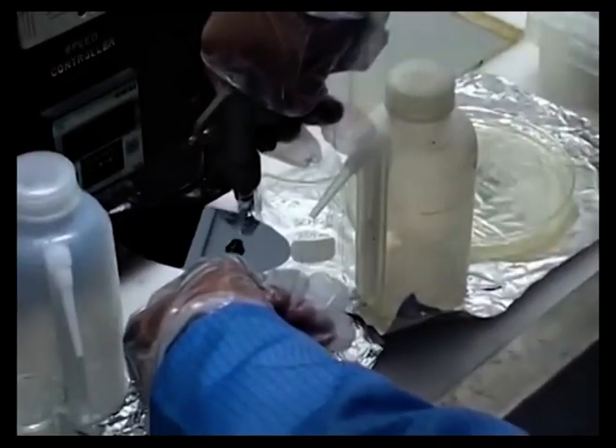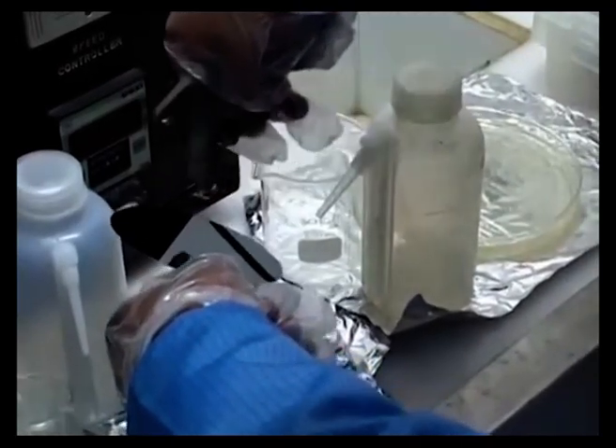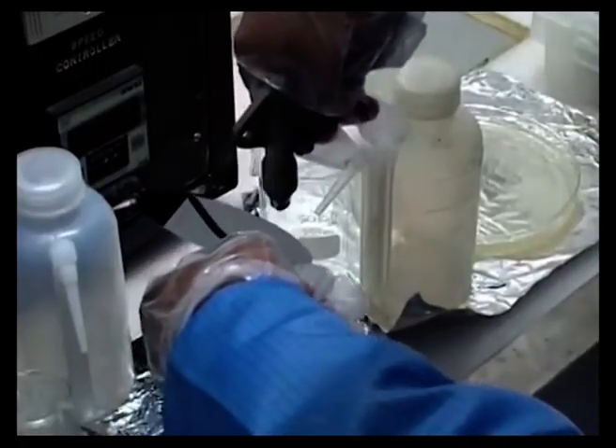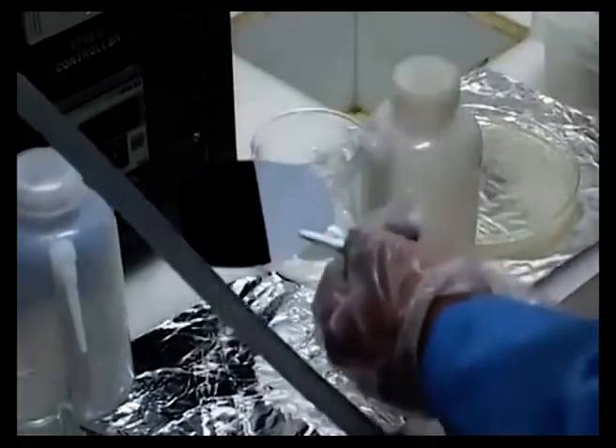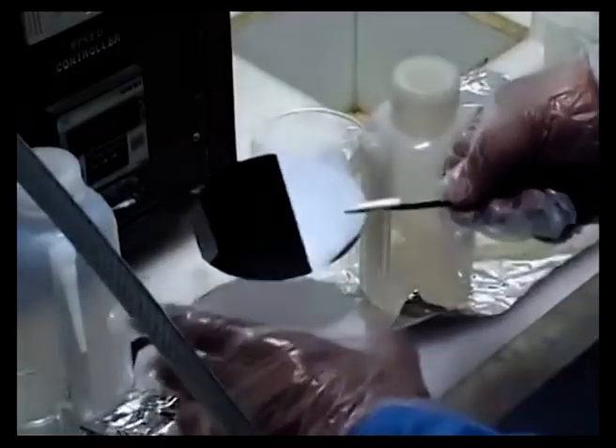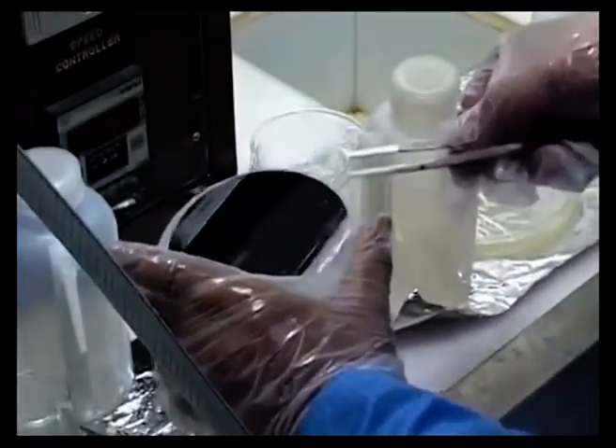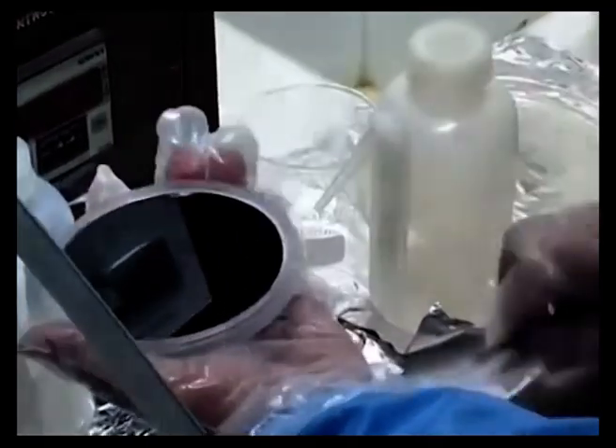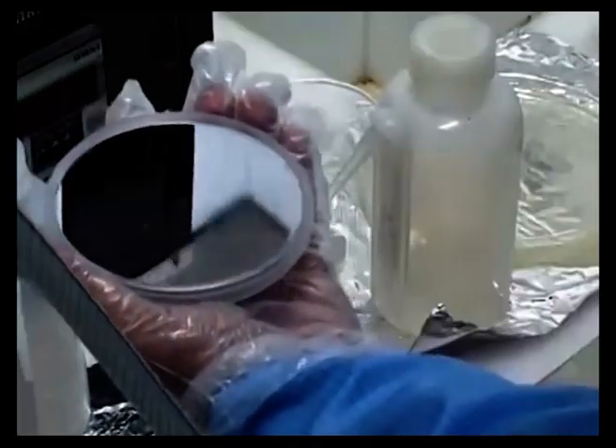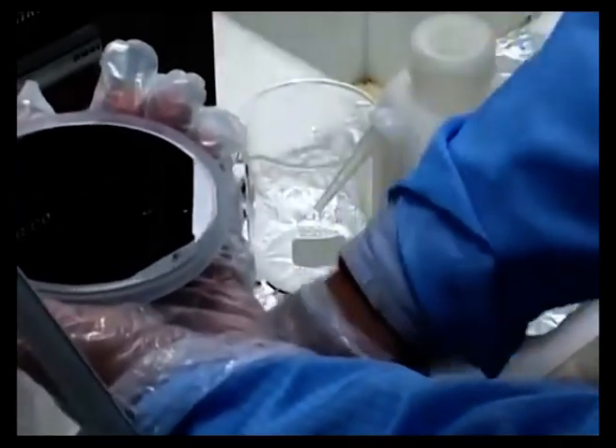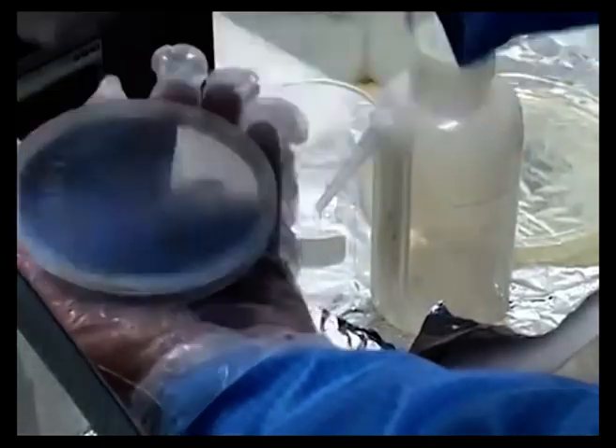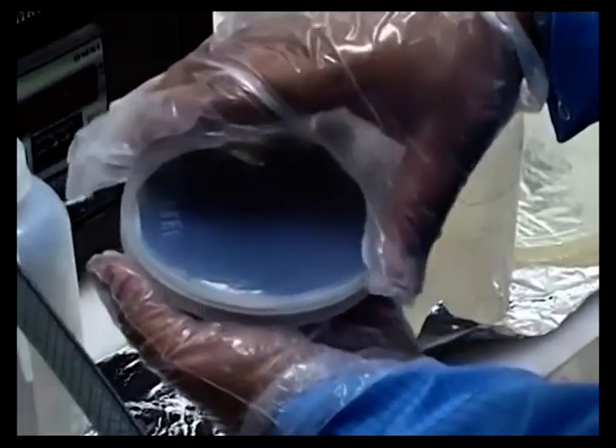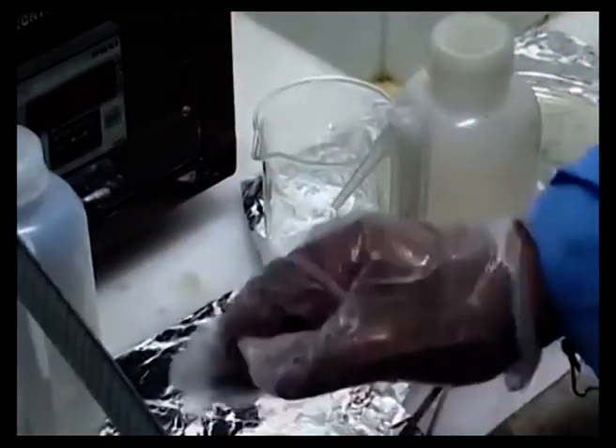So we put this sample, this clean sample, back into the wafer box, as you can see, and then we'll actually do a heat treatment of this particular wafer, so that it can get rid of all the water from the surface, and that way we have a completely dehydrated surface. We need to cover it at this stage, because the moment we move it out of this clean area, it can again become dusted and the contamination of the surface may happen. So this is how the Piranha cleaning process of the wafer is done.